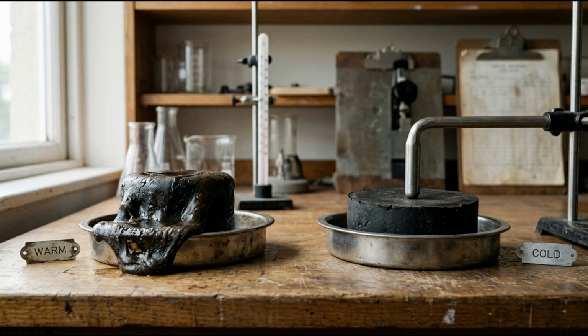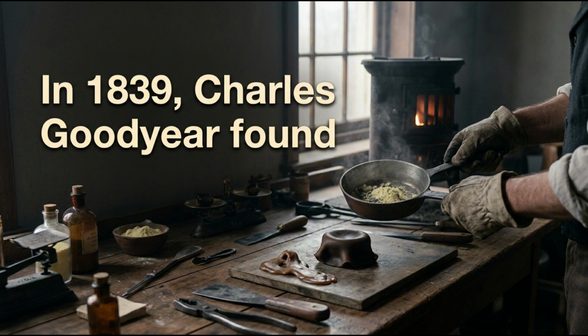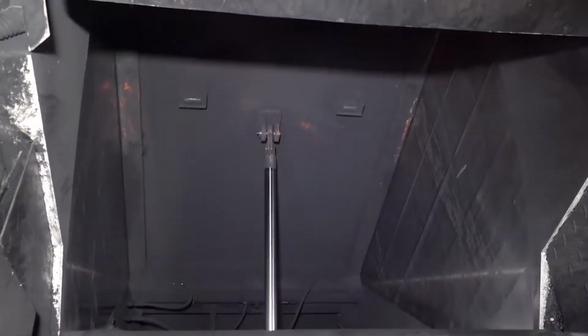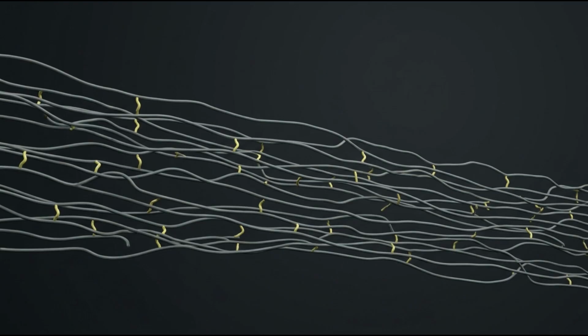Untreated natural rubber can become soft and sticky in hot weather, then harden when the temperature falls. In 1839, Charles Goodyear found that heating rubber with sulfur and other ingredients made it far more stable. The process became known as vulcanization. Sulfur helps create connections between the long polymer chains inside rubber. These crosslinks limit how freely the chains can slide. The material can still stretch and flex, but it becomes better able to recover instead of flowing apart or remaining permanently deformed. That discovery helped make durable pneumatic tires possible.